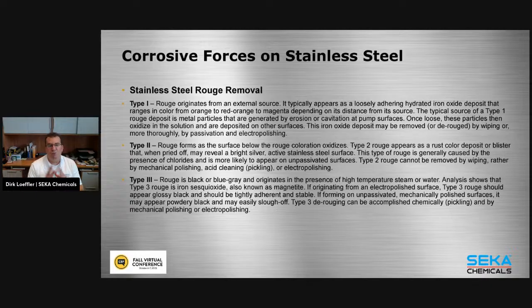Again, we talked about the type 2. So pretty much every rouging can be fixed, but it takes different approaches. Type 1 generally can sometimes just be wiped off, because keep in mind, it didn't happen right there. It was actually carried in and just deposited itself. So we can generally wipe, or, worst case scenario, run a passivation. In some cases, electropolishing, but generally passivation and wiping will take it off. Type 2 rouging, generally here we're looking at pickling. When I say pickling, low nitric acid, which we normally use for passivation, would not be enough. You probably need to use a hydrofluoric nitric blend.